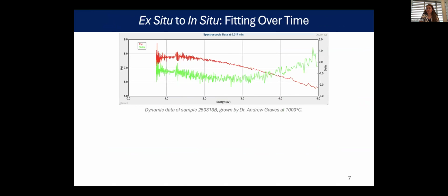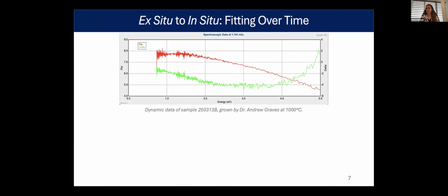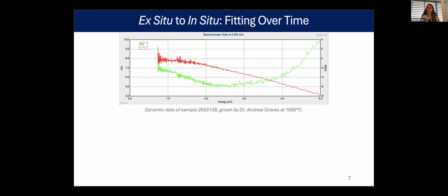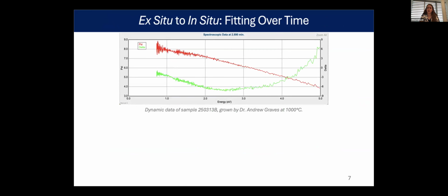So then we've been looking at these static single time slice psi and delta spectra. We can also take data that goes over time. So this is some dynamic data from a growth where we have a different spectra taken at each moment, and we can put those together. So instead of just having the one time slice and fitting at that time slice for the coverage percentage, we can then get a function of time and see how it's developing based on how the spectra change. Then we can compare that to the AFM confirmed data. So let's look at that graph.